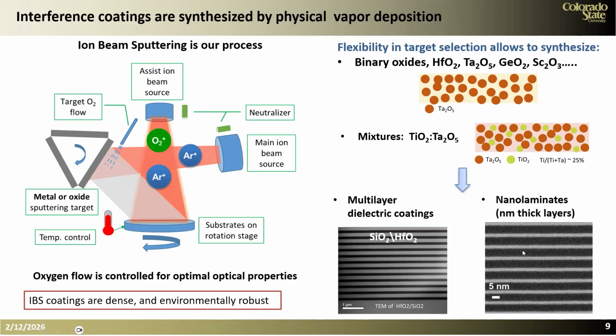We can also make other types of materials that are called nanolaminates. And here what we do is we grow very thin layers. This scale is 5 nanometers. Here this bar was 1 micron. So notice that the thickness of these layers is of the order of 2 or 3 nanometers, and this one is thicker. And then we stack them. And then we use these layers to replace, for example, the high index hafnia layer in a coating.